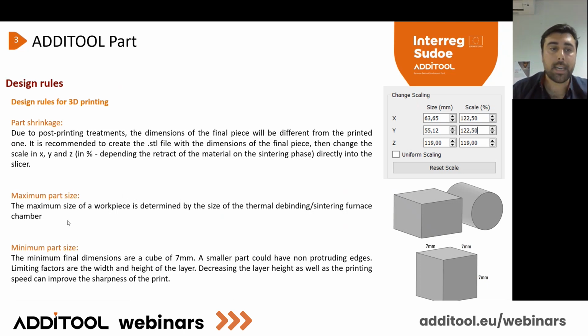So you will have a maximum part size. An important trick also: the maximum size does not depend on your printing machine, but on your debinding and sintering furnace. This is very important, because if your machine can print 500 millimeters and your oven only 100, the maximum size will be 100. And it's very complicated on the market to find a sinter and debinder oven of more than 100 millimeters in diameter. So that conditions your maximum size, and the minimum is about 7 millimeters.